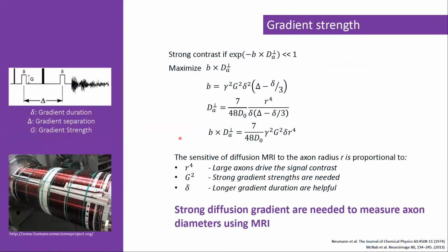But what do we need for this? And that's where gradient tricks come into play, where hardware development comes into play. If we want to be able to measure axon diameters, we need to create contrast and achieve a good contrast to noise ratio by maximizing the B value times the intraaxonal diffusivity, because only then this exponent will be smaller than 1, and we can be hopeful to measure it. The B value is a known feature in diffusion MRI, which is basically a convoluted metric that includes the diffusion gradient strength, the diffusion gradient duration, and the separation, which relates to the diffusion time.